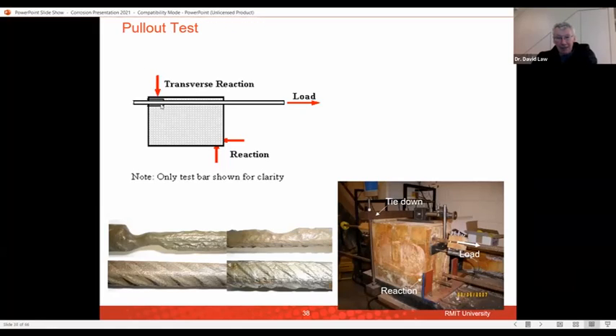This is how we would do the test. So they're clamped, but we've got that bond breaker here to make sure there's no reaction, and we pull them out in a sort of perpendicular direction, and this shows you sort of the section of some of the bars that we took out.